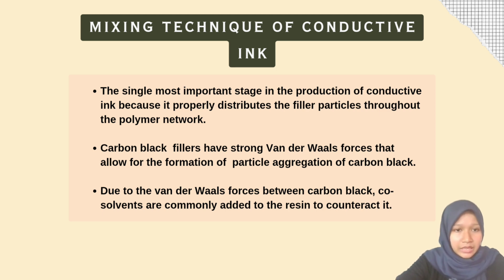The mixing technique of this study is the most important stage in production of conductive ink because it properly distributes the filler particles throughout the polymer network. Carbon black filler has strong van der Waals forces that allow the formation of particle aggregation of carbon black. Due to the van der Waals forces between carbon black, co-solvents are commonly added to the resin to counteract it.